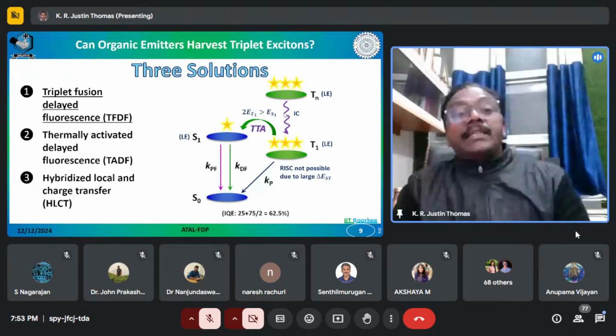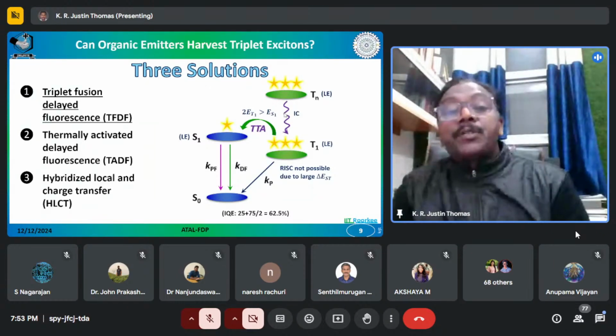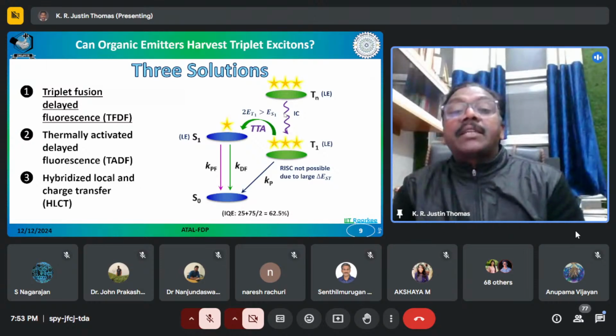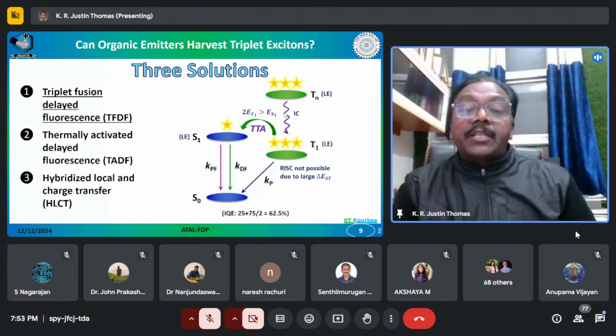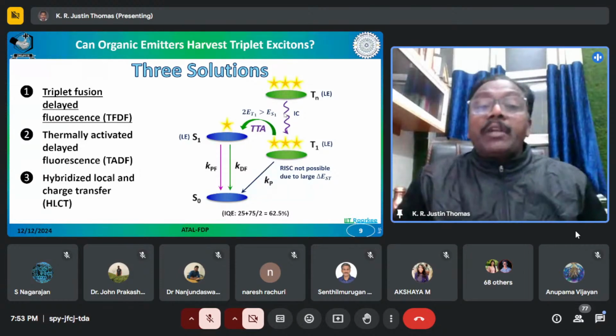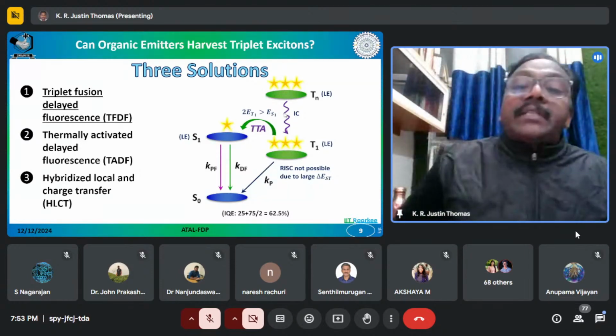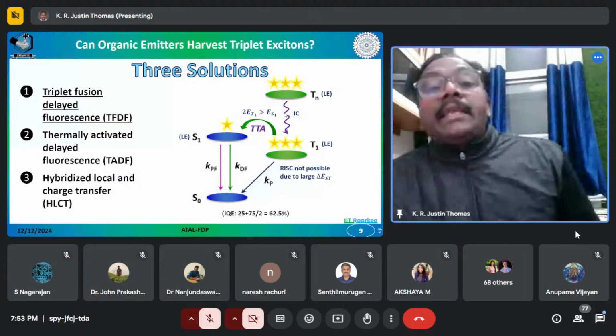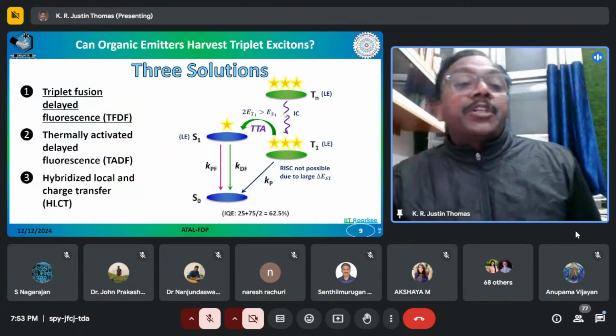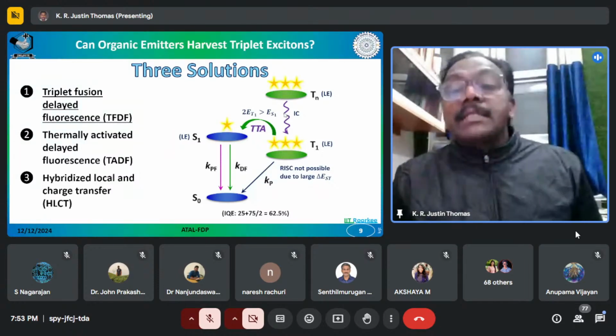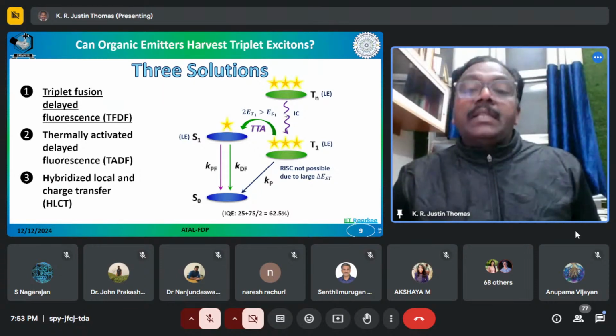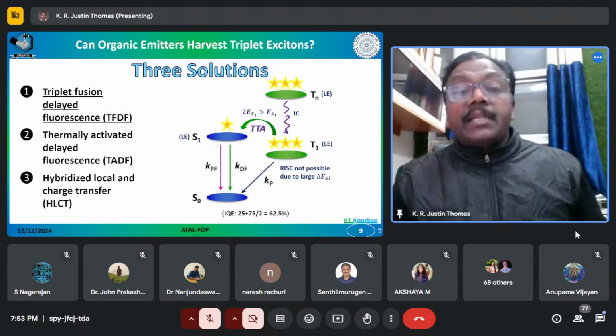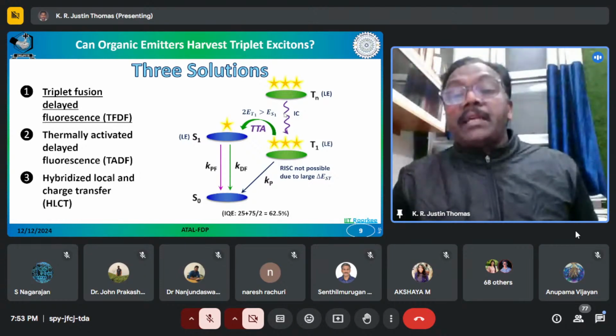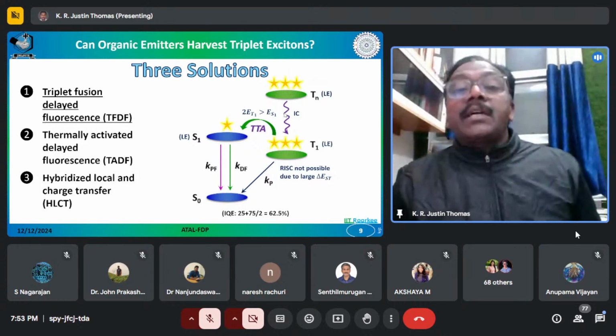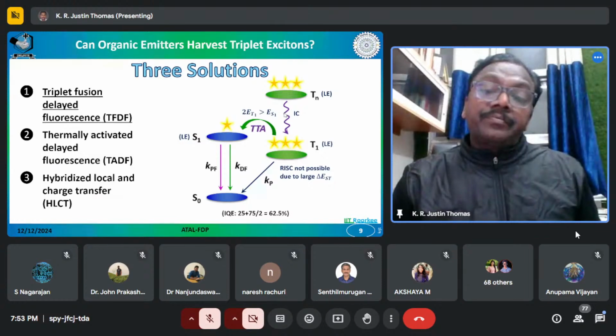So the efficiency in these systems will be 25 plus 75 by 2, because out of the two triplet excited states, only one is converted to the singlet excited state. So you have to divide by 2. So overall, the internal quantum efficiency that you can realize in the triplet fusion delayed fluorescent materials is 62.5%. Nevertheless, it's good. It's not very good, but it is good because you are able to harvest half of the triplet excitons.